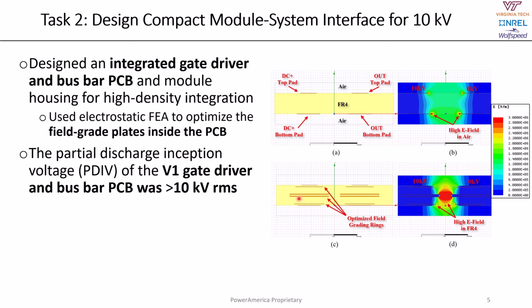And so what we've done is we've explored unique field grading optimization techniques to look at designing field grading plates that are internal to the FR4. And by doing this, we can draw the peak electric field inside the FR4, which has higher dielectric breakdown strength than the air. And you can see here from the electric field distribution plot from FEA simulation that the electric field strength in the air has been reduced by almost half.